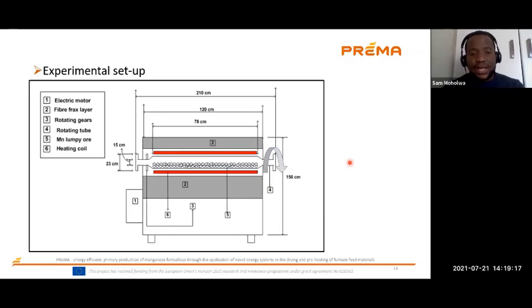Here we have the typical cross-sectional view of the kiln that we used in these experiments. Here, as you can see, we have the rotating tube of the kiln. We have the heating elements here. Then here, number 2, we have some insulation to prevent unnecessary loss of heat. Here we have a DC motor. This DC motor is used to drive the rotation of the kiln. This DC motor has a knob which you can turn either clockwise or anti-clockwise to adjust the rotational speed of this kiln.